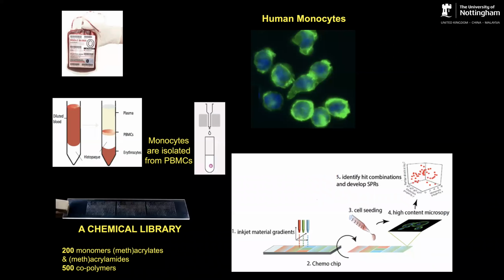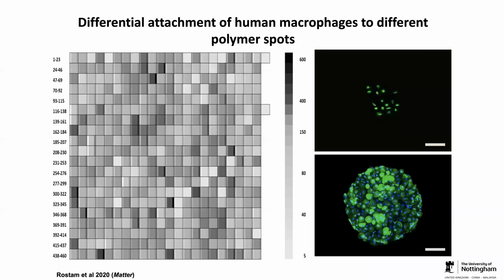The workflow is that we separate monocytes from peripheral blood, and these are the precursors of macrophages. They are seeded on these polymer arrays, and then we use microscopy to initially look at cell attachment, followed by more characterization of the cells. But even at the level of cell attachment, you can see that there is diverse cell attachment potential, starting from polymers that only attract a handful of cells to those with hundreds of cells. And that on its own could have major implications in terms of how a particular polymer will interact with the immune system when implanted.